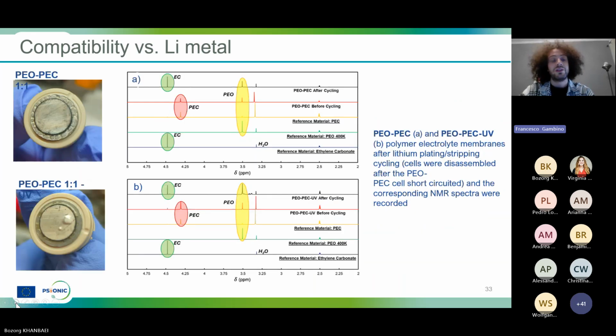Also, we opened the cell after plating and stripping, and we tested with NMR. So the opaque membrane, as I showed you before, was showing a gel-like compound after cycling. And in fact, the NMR revealed that before cycling, there are the peaks that can be attributed to PEC and PEO. But after cycling, there is a new peak that is demonstrated to be ethylene carbonate that is appearing, confirming that the polyethylene carbonate is depolymerizing, forming the ethylene carbonate monomer and causing a loss of solidity of our membrane.